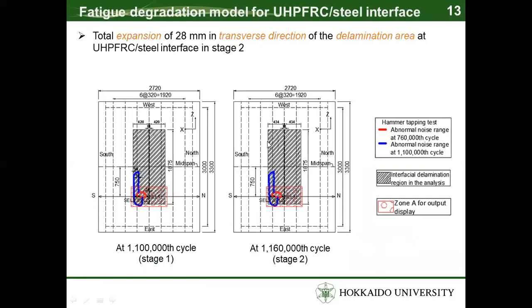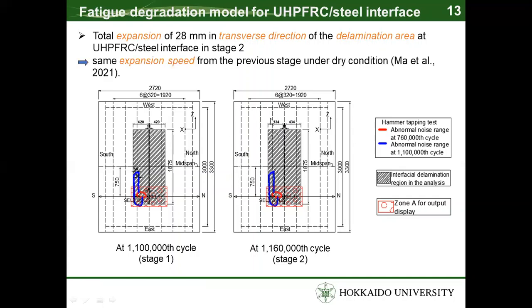Fatigue degradation model of UHPFRC-steel interface. The total expansion of 28 mm in transverse directions of the delamination area at the interface between UHPFRC and steel in this stage is the same expansion speed as in the previous stage under dry conditions.